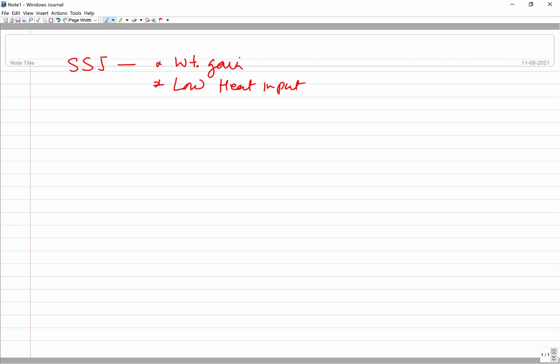Although in SSJ also we have low heat input and high heat input processes. In low heat input processes, say, the temperature rise may not be 150 degrees centigrade, and in the high heat input process, although base metals still remain in the solid state, the temperature rise may be well above the recrystallization temperature. So those you may call a high heat input process. But as compared to fusion welding, the heat input is low. And another good part related with solid state joining is that the thermal damage to the base metal, or parent metals, is very negligible, or very less,